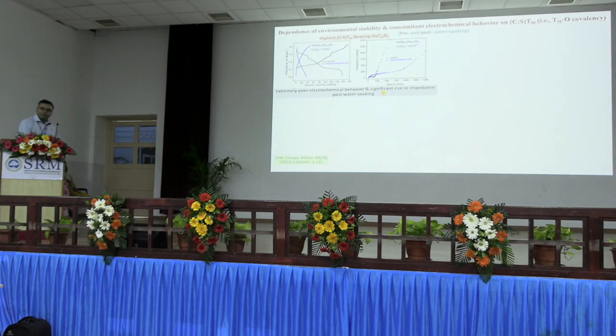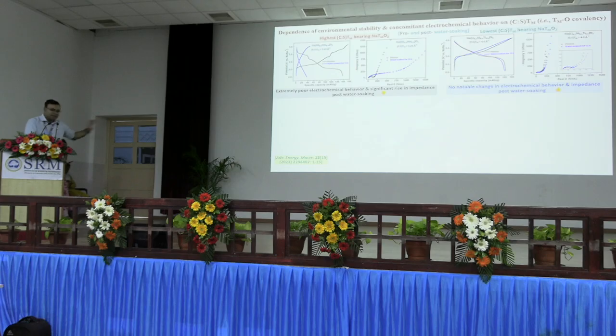So now when it comes to the electrochemical performance, the one with the highest charge to size ratio of the cation combination in the transition metal layer shows no electrochemical performance upon being soaked in water for 12 hours, and we can see a huge increment in the impedance. Whereas the one with the lowest charge to size ratio, which we found to be water stable, the electrochemistry also proves that. There is no change in the electrochemical behavior even after 12 hours of water soaking. The potential profiles, the capacity as well as the impedance tell exactly that.